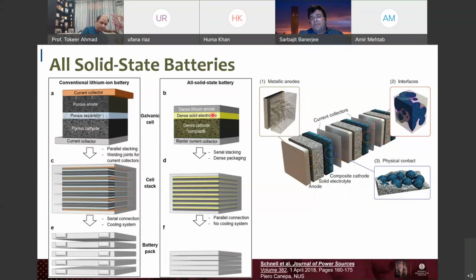taking a lithium anode and a solid electrolyte and matching it with a composite cathode, and this eliminates the need for necessarily having a separator and having a large porous anode architecture. So you can essentially use a thin metal lithium foil and access the full capacity of lithium. So there's a lot of excitement, particularly in the electric vehicle space.